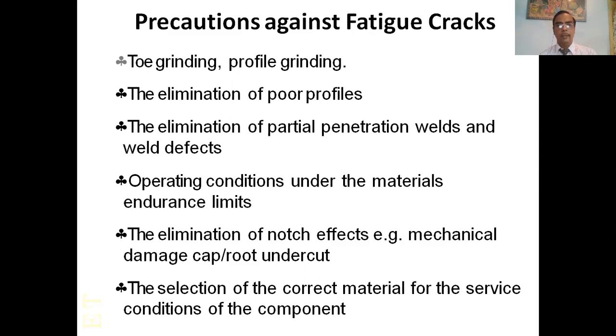Precautions against fatigue crack: toe grinding, profile grinding, elimination of poor profiles, elimination of partial penetration welds and weld defects, operating conditions under the material's endurance limit, elimination of notch defects such as mechanical damage, cap or root undercut, and selection of the correct material for the service conditions of the component.